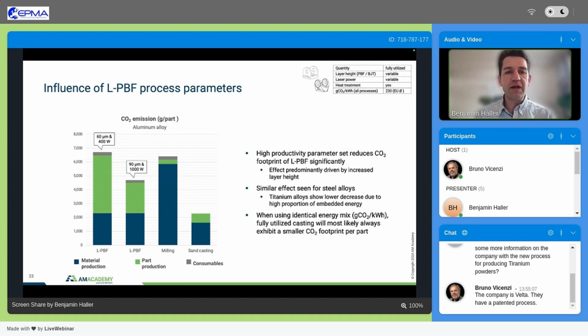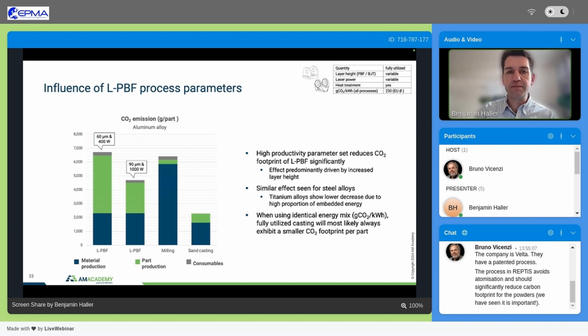Higher laser power here. What we see in the industry happening right now is not only increasing the layer thickness and using a stronger laser, but also different beam profiles. For example, a ring-shaped beam profile that speeds up the process even more, and there even with a lower laser power, you can reduce the CO2 footprint.